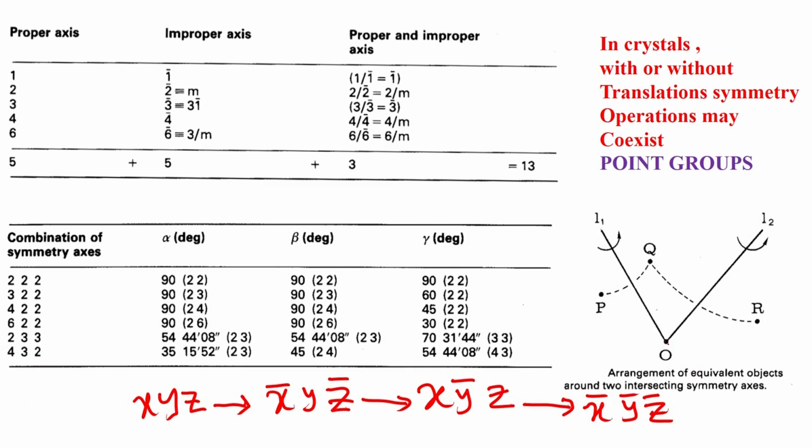It should be an axis which will go here such that now R gets related to P by another two-fold axis. So, R and P now get related to each other by another two-fold axis, and that is the point which we have to think of and we should remember. Whenever there are two rotation axes intersecting at a point, a third rotation axis is automatically generated.